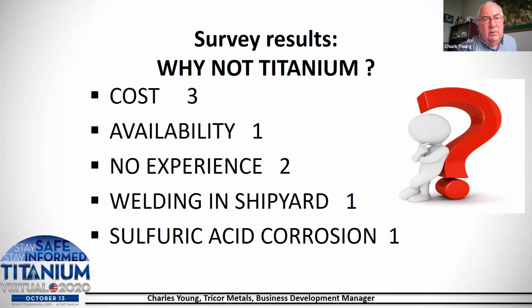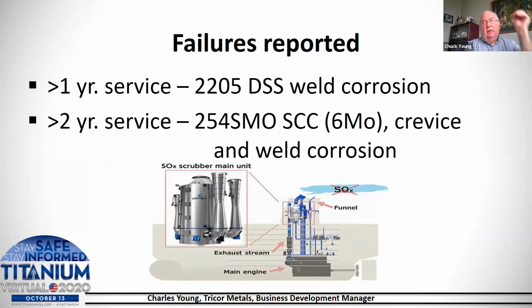And these are typical responses when the nickel alloy and stainless alloy people have been talking. These are their talking points about why not titanium. So they have shown the industry that titanium may not be good, and these are the reasons why. So this is something we have to correct. In looking at the survey, there were a couple of failures reported.